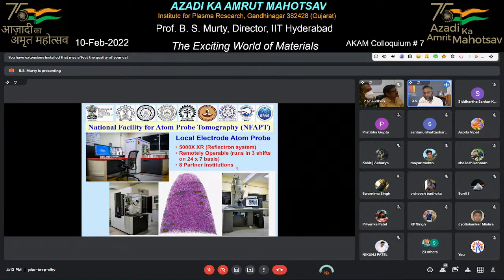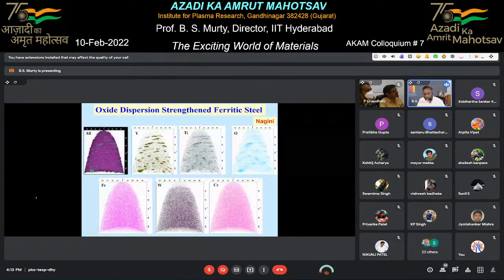This is something we are able to demonstrate, and quite a number of people are using it and getting an exceedingly good understanding of the materials. For example, this is one such ODS steel where you can see iron, tungsten, chromium, all of them uniformly distributed inside the sample, but yttrium, titanium and oxygen are segregated into that particle. So it is a Y2Ti2O7 kind of particle. We have been able to prove this from the composition of those individual particles. So you can do composition analysis at a very nano scale. No SEM EDS can do this, and it is possible with such an atom probe.